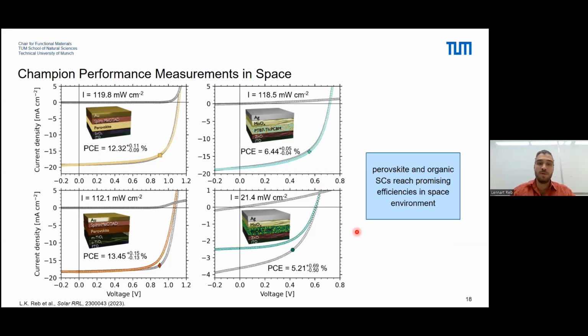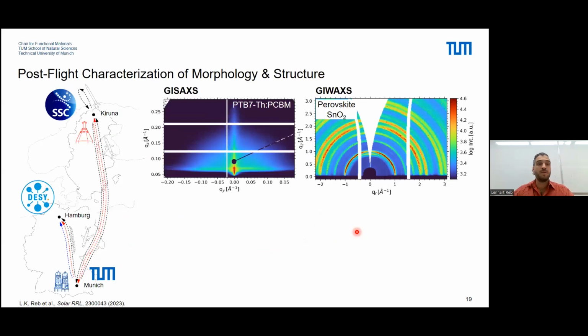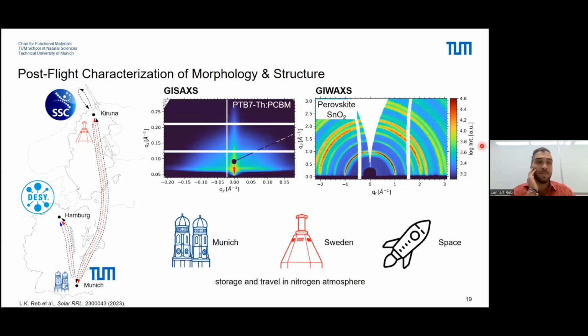So this is actually quite encouraging. But still we have some differences, and the question arises now, did the experiment have an influence on the solar cells? And for this, we performed post-flight characterization of the morphology and the structure of these cells. And we did it the following way. So we have 3 sample groups, one that stayed in Munich in the glove box, one travel group that traveled to the experiment but didn't fly, and one group that flew with the rocket, and we brought it all back, and then went together with all the 3 packages to Hamburg and to DESY and started our measurements.